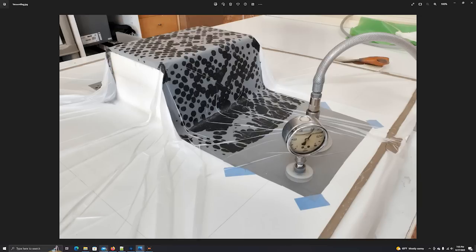So usually there's a form of NDI, non-destructive inspection, or NDT, non-destructive testing. And in the case of carbon fiber, they usually use a type of ultrasonic inspection where they bounce sound waves through the fabric, and then they can tell where the voids or delaminations or weak spots are in the fabric. And if there are any, they can be cut out and repaired.